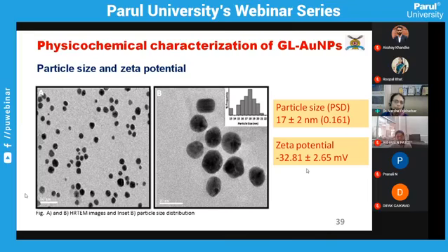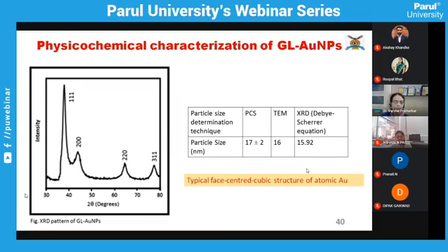Now this is obviously because glycyrrhizin, which is a saponin, has hydroxyl and carboxyl groups, and there are chances of free carboxyl groups on the surface, which render a negative charge to the surface. The XRD pattern indicated that it is typical gold in highly crystalline form with a typical face-centered cubic atomic structure, with the peak of highest intensity confirming the face-centered cubic structure.